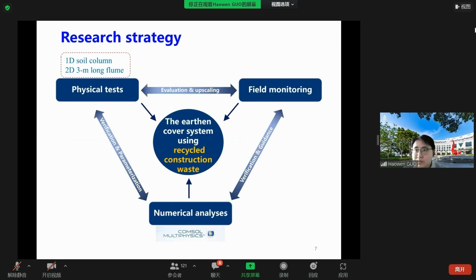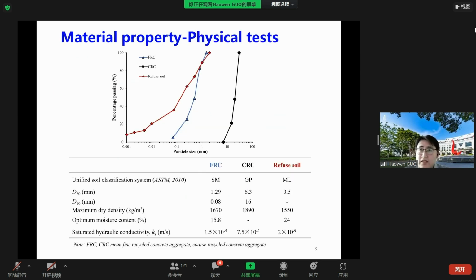So to tackle this limitation, this study proposed a multi-dimensional research program including 1D soil column tests, 2D flume tests, field monitoring, as well as numerical analysis. This slide shows the material properties we used in the physical models. Fine recycled concrete is used as material for the top layer, coarse recycled concrete for the middle layer, and we use refuse soil for the bottom layer. From the bottom table, we can find that those materials have very high contrast in permeability, so that it can ensure the performance of the cover system.